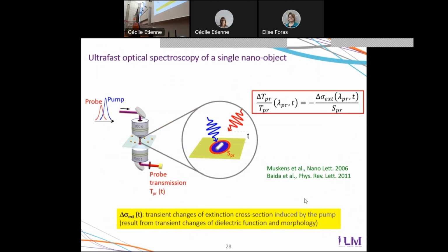Okay, so regarding time-resolved experiments, I've already discussed this type of experiment in general. When they are applied on single nanoparticles, what has to be done is to overlap a very focused pump beam with a very focused probe beam, and to overlap them on the single nanoparticle. So these are not easy experiments because one needs to preserve this alignment as a function of time. In these single particle experiments, I should also say that the signal that we measure is actually directly proportional to the transient change of the extinction cross-section of the object as a function of time, which results from changes of dielectric function and morphology.